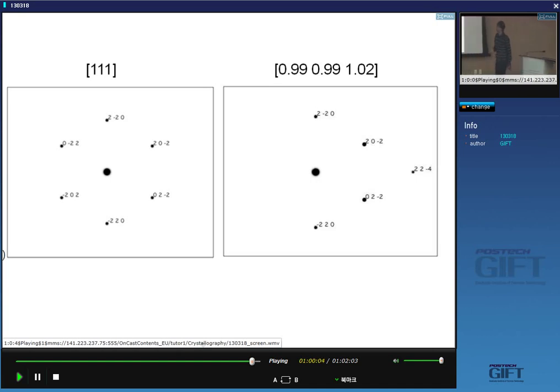This is just to show you that if the Ewald sphere intersects the origin symmetrically, then you pick up spots on both sides. But if you tilt the beam away from 111, so this is tilted, then you will intersect one side more than the other, and therefore you get a pattern which looks a little bit strange. Okay, so here you are not satisfying the Bragg condition, here you are. Just tilting the Ewald sphere relative to the reciprocal lattice.